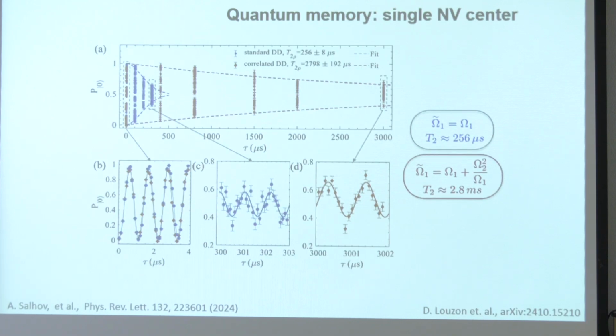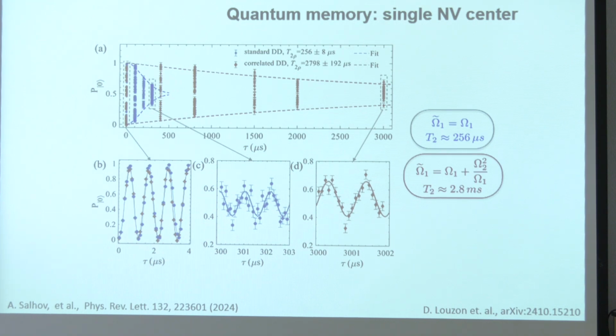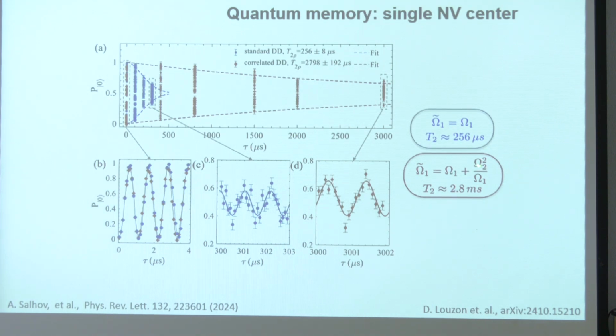I show you here an example of experiments where we detuned the second order drive. I show you now Rabi flops, like the life of a qubit in time, for a conventional single drive, and this is now the decay of the qubit after a few hundreds of microseconds, not so bad, similar to what we have seen before. And if you apply this double drive scheme with the right detuning, the noises of the microwave cancel, and the T2 time goes to about 2.8 milliseconds, so it's about an order of magnitude better.